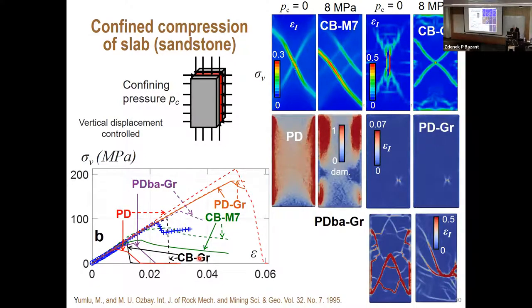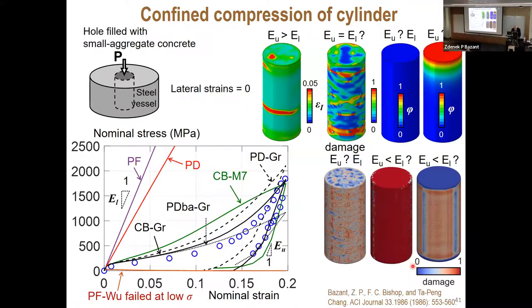Now the same picture is done for other models. Peridynamics, same diagram, these curves. You see they don't work, and you can see in the diagrams that the patterns of damage are incorrect, as you see here. Peridynamics gives nothing here. Bond-associated PD, so incorrect. So all these models fail this test.